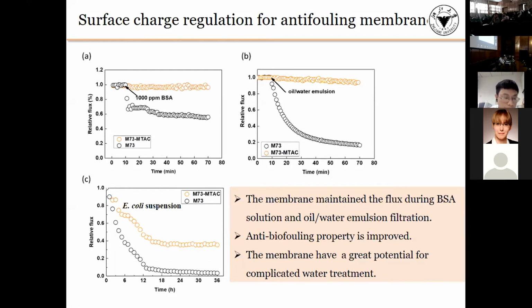Here we have some explanation. Because we introduce the MTAC onto the membrane, the hydrophilic component further improves surface hydrophilicity. Meanwhile, MTAC neutralizes the surface charge. In addition, a polyampholytic copolymer was formed. Such a copolymer is recognized as an antifouling component. Therefore, a more hydrophilic and non-charged surface containing polyampholytic copolymer was formed through a simple surface grafting method.